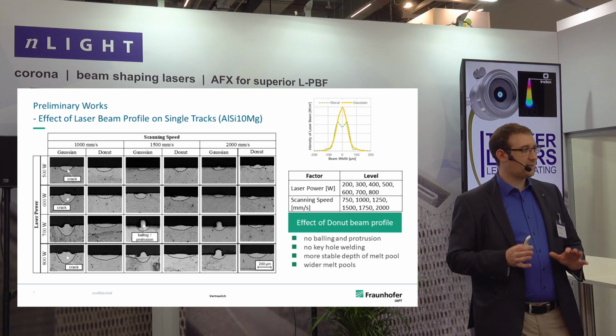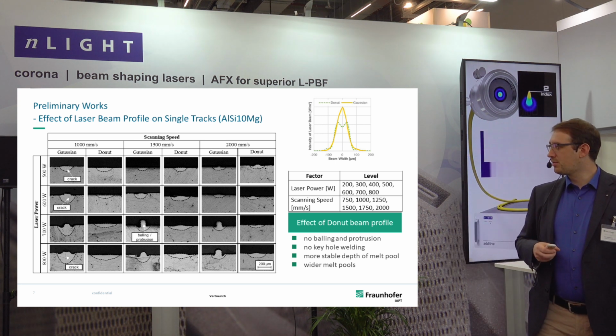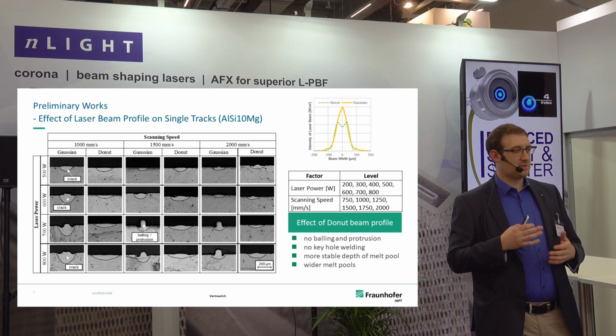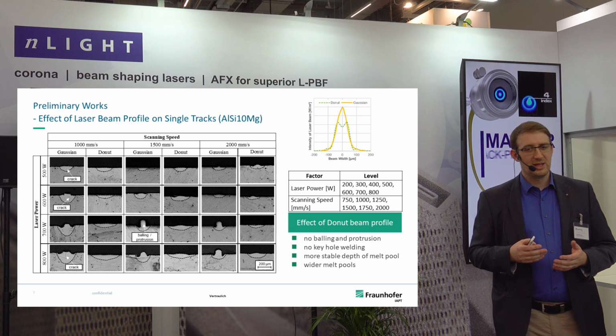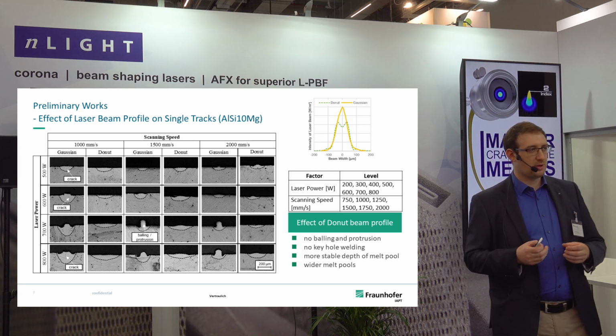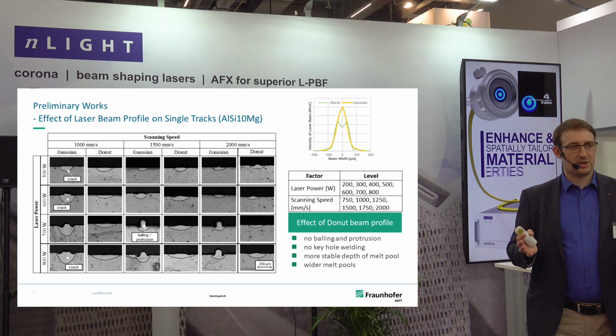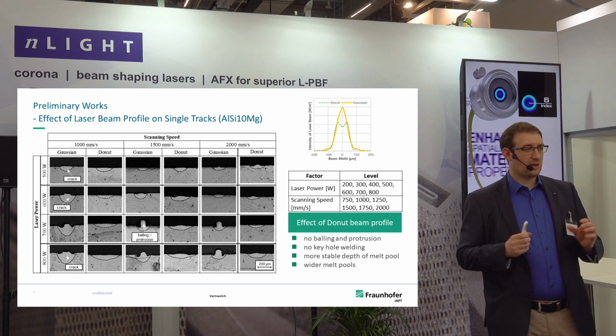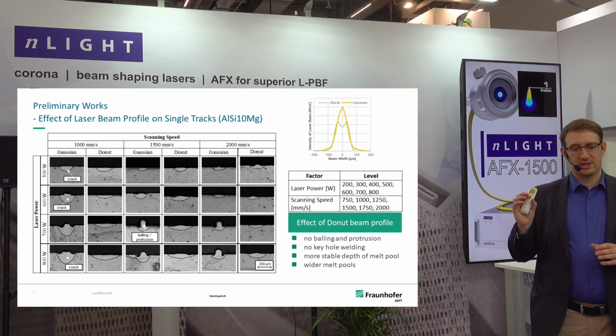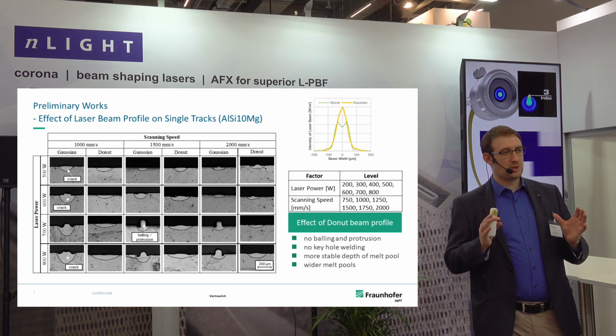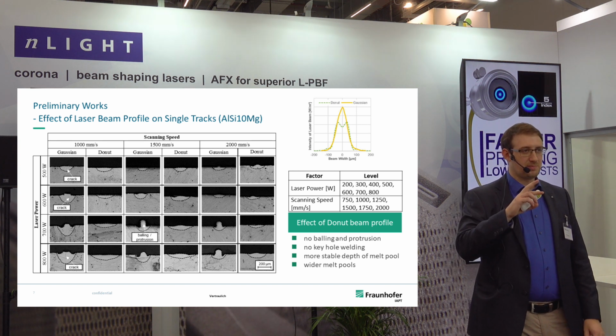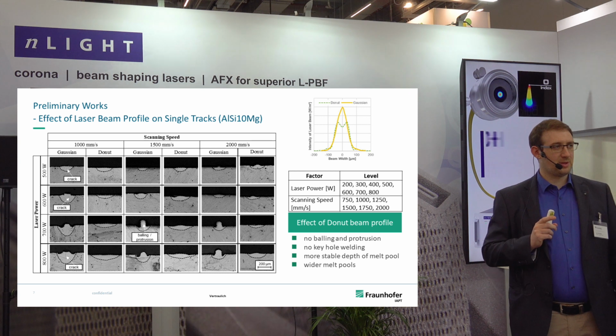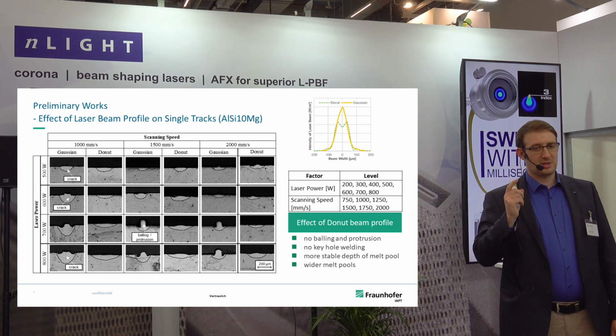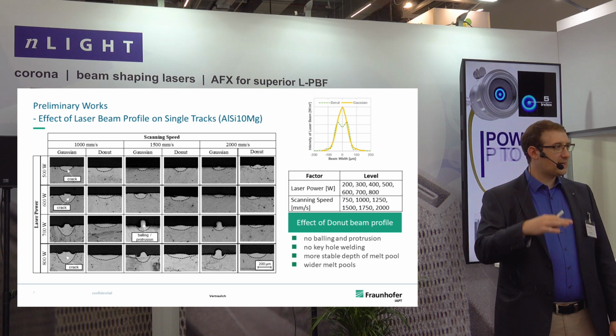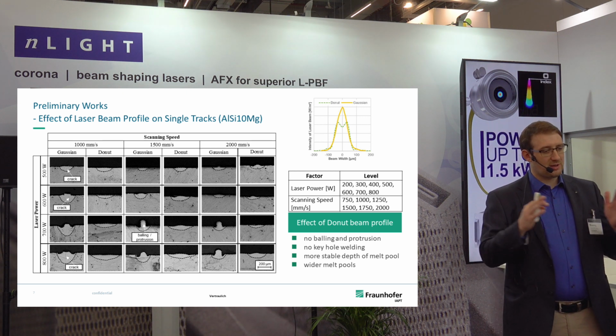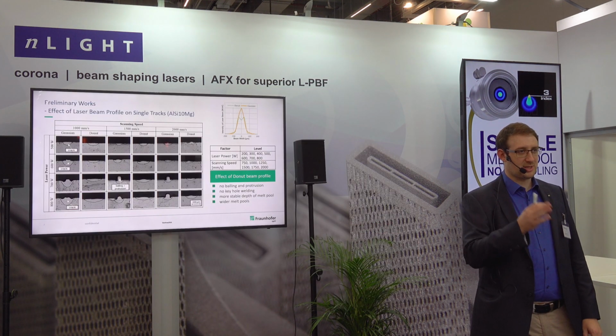I want to highlight on this slide that for the Gaussian profile on the left, you can see some defects like protrusion or cracking, while for the donut profile this was not visible for the wide range of combinations of process parameters we used. Also, quite interesting, for the donut profile the melt pool gets wider but not so deep. This is interesting if we are thinking about productivity, because we don't want to melt several layers of powder again and again, but we want a wide melt pool so we have fewer hatches.